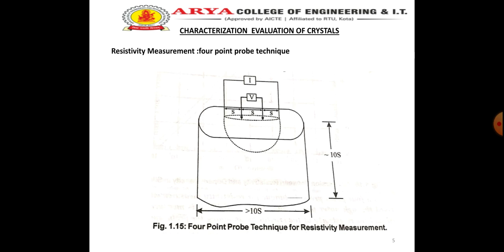After growth, the crystal is usually weighed, then inspected visually. Growth crystalline imperfections such as twinning are apparent to the unaided eye. Sections of ingots containing such defects are cut from the boule, and from the butt end of the ingot a slice is cut from that portion and then etched to reveal defects such as dislocations.